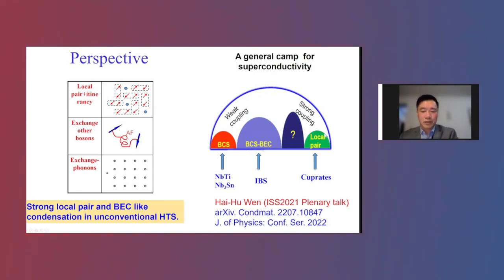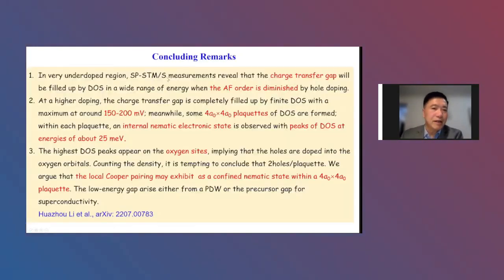Okay, so this is my final picture to conclude our data. So then let me come to the conclusion. The first is that in the very underdoped region, we used a spin-polarized STM to reveal for the first time that the charge transfer gap will be filled up by density of states in a wide range of energy when the antiferromagnetic order is diminished. And the antiferromagnetic order is viewed directly for the first time by the spin-polarized STM. At a higher doping, the charge transfer gap is completely filled by DOS, with a hump in this region corresponding to the J value, in the same scale.